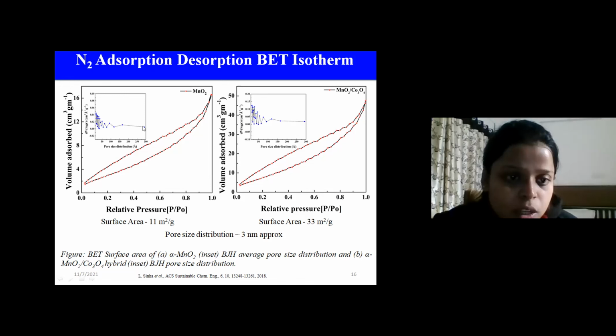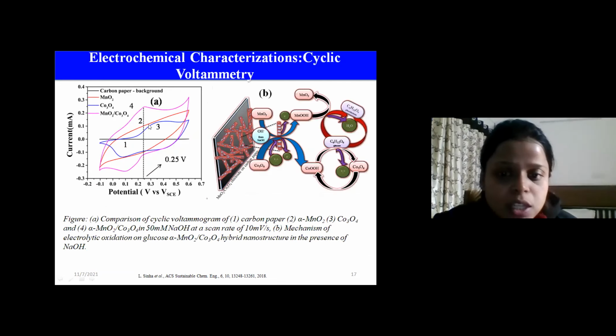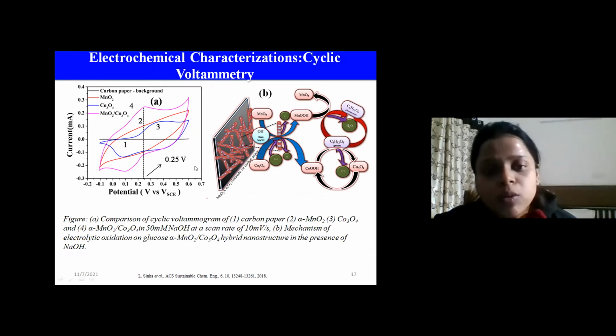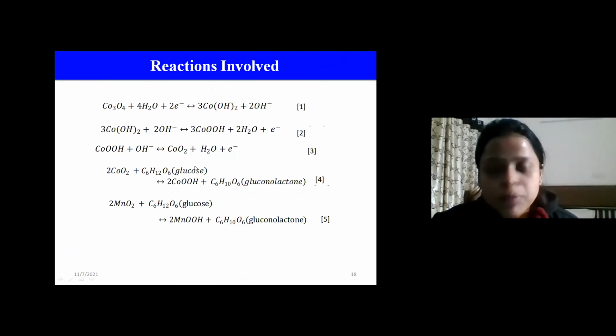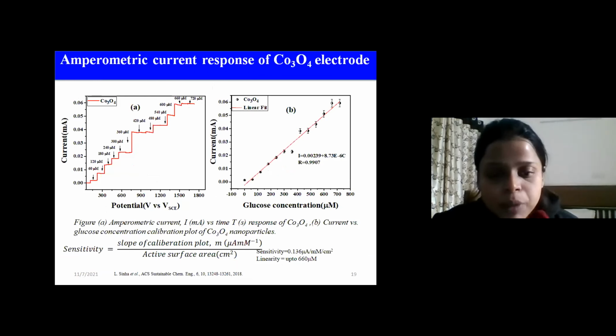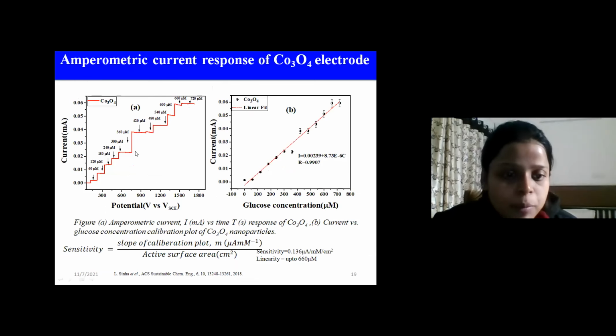Red curve is for the alpha MnO2, and it is electrochemically silent in the electrolyte, whereas the Co3O4 nanoparticle is active, and the combination of these two nanomaterials is giving a high oxidation rate for the hybrid nanomaterial, and the oxidation potential is 0.25 volt. So for the chronoamperometry measurement, we have fixed this potential, 0.25 volt.